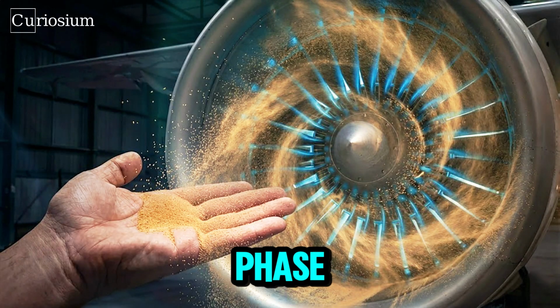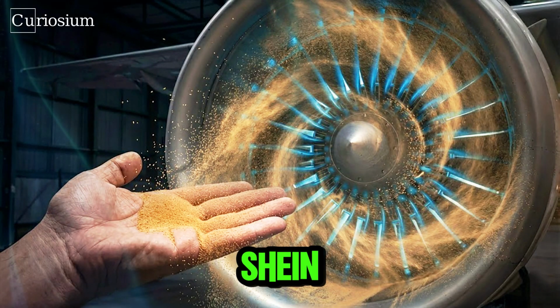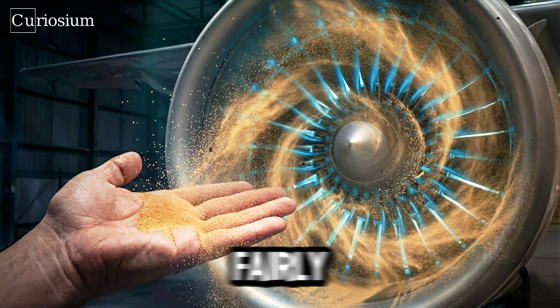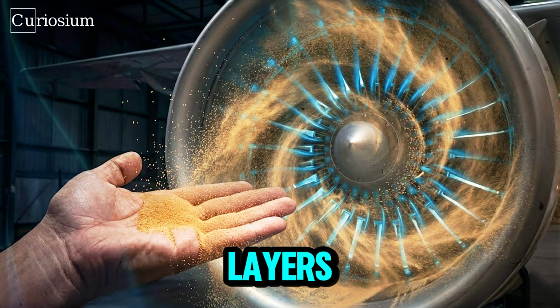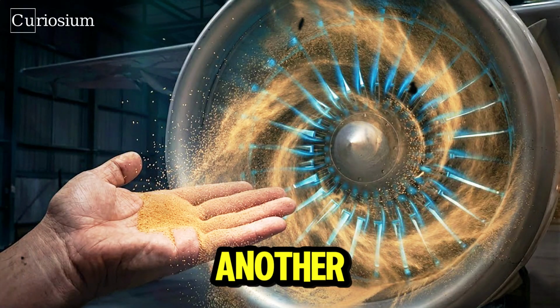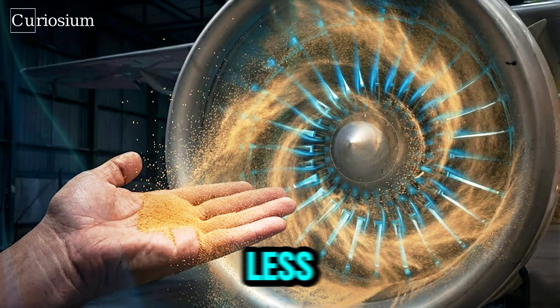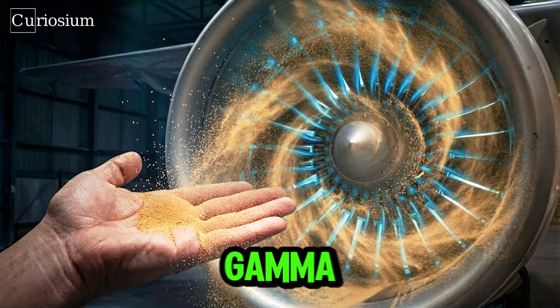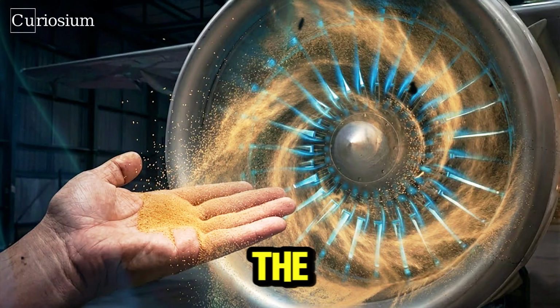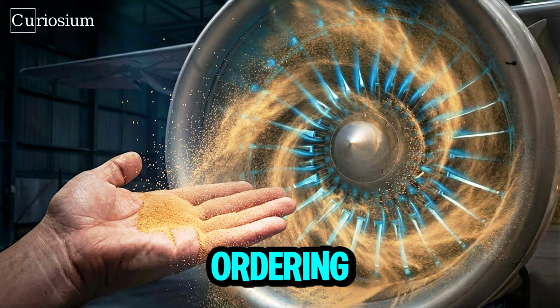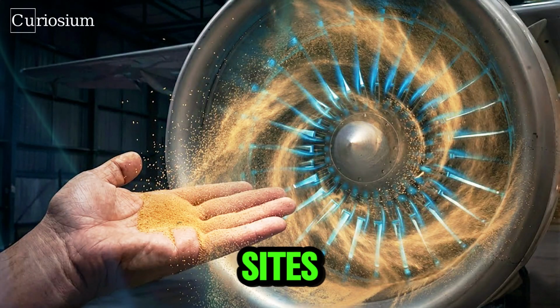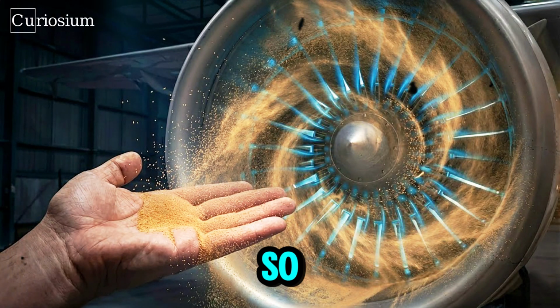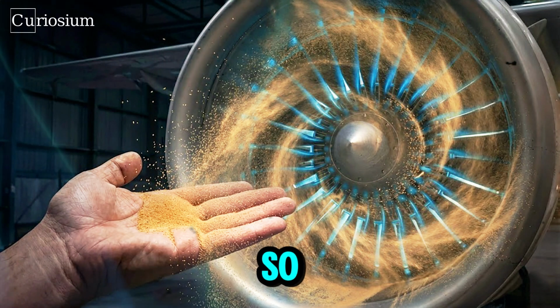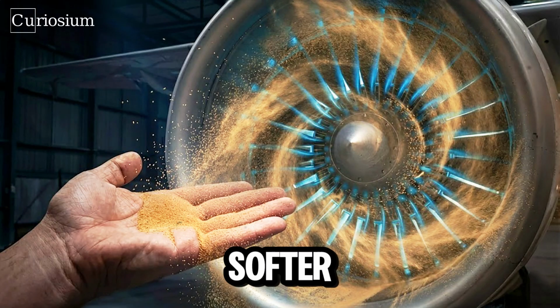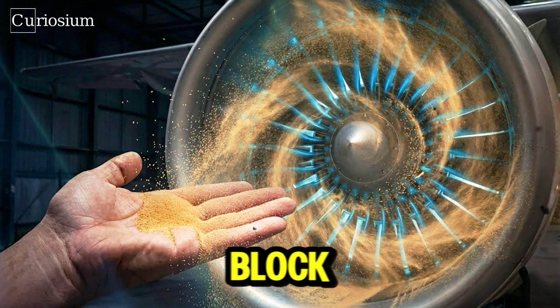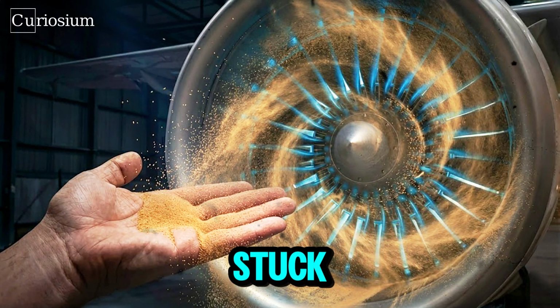In the gamma phase, a dislocation can glide fairly easily. Layers of atoms can shear past one another and leave the structure looking more or less the same. In the gamma prime blocks, trying to shear the lattice would scramble that perfect ordering, putting atoms into the wrong sites. That costs energy, so the lattice resists it. So, when a dislocation traveling through a softer gamma region hits a gamma prime block, it tends to get stuck.